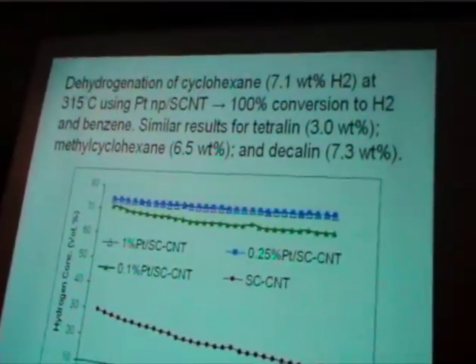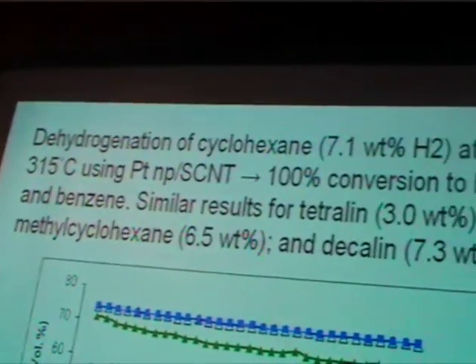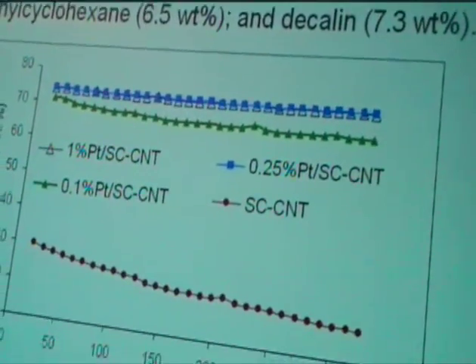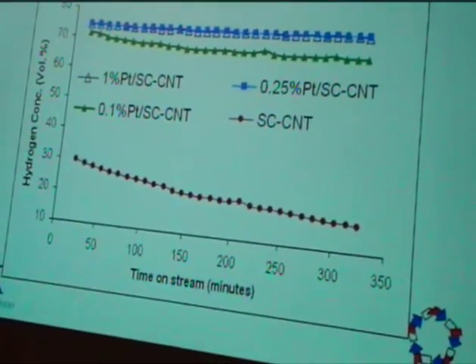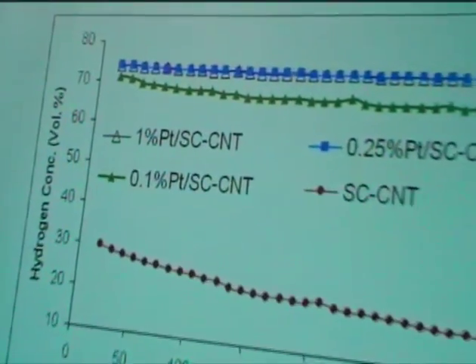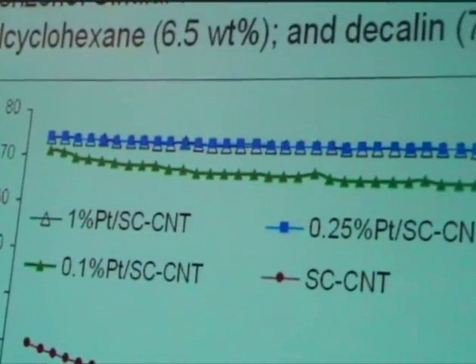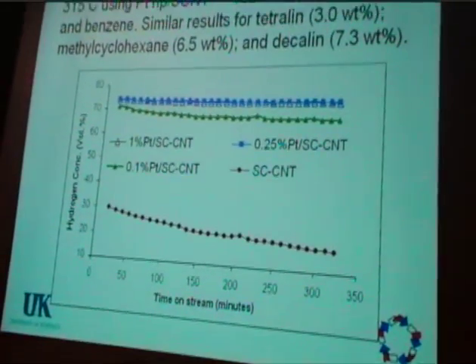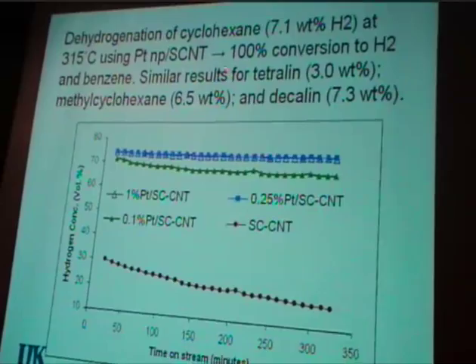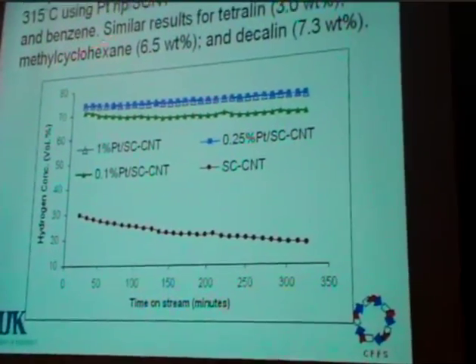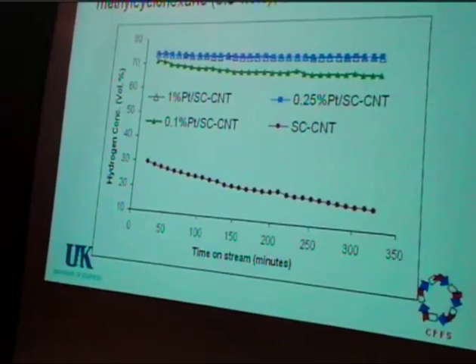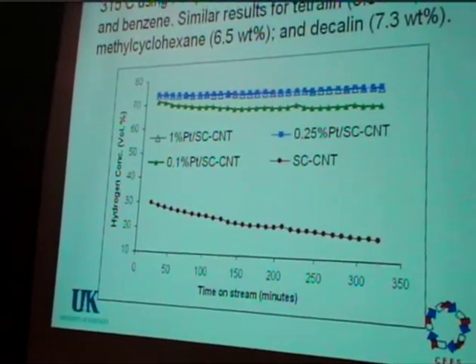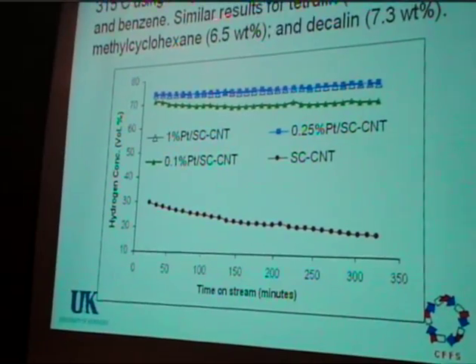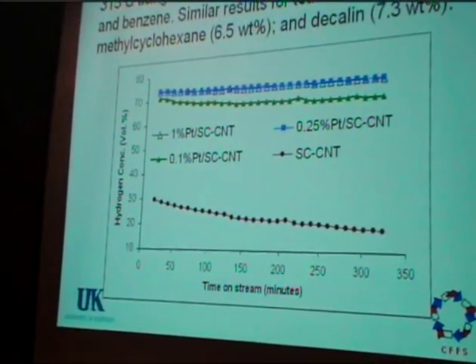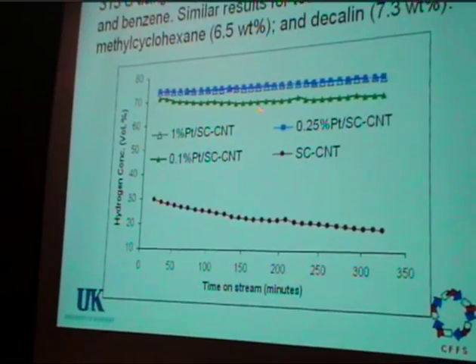But we have done a little bit of catalysis work, and one thing that might be of interest is producing hydrogen using these sorts of catalysts. So we put some platinum nanoparticles onto stacked-cup carbon nanotubes, and at a little over 300 degrees C, you can decompose a lot of cycloalkanes and produce pure hydrogen and aromatics. Cyclohexane is the most obvious one. It decomposes to hydrogen and benzene, and then you get similar results for tetralin, methyl cyclohexane, and decalin.